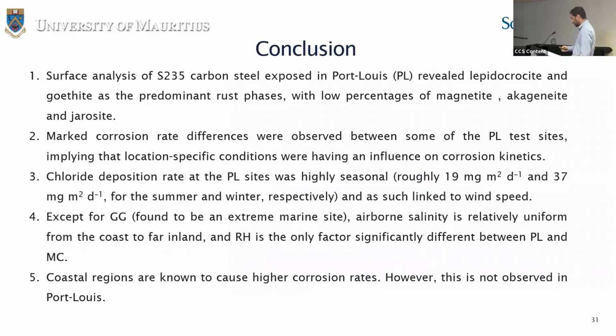To conclude, following characterization of corrosion products, it was seen that the conditions at the different sites in Port-Louis were not adequate for formation of a significant amount of akageneite and magnetite rust phases, which require high chloride content and acidic conditions of the atmosphere. However, there were low percentages of these compounds, which do not form at the rust-metal interface. All the sites fall in the same corrosivity category. However, marked differences were obtained in corrosion rates. This shows that location-specific conditions, such as sulfur dioxide level and chloride deposition rate, were having an effect on corrosion rate.